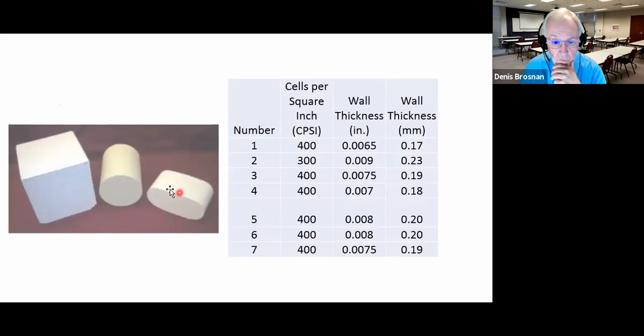The honeycomb products come in different shapes and sizes and all have open cells for the gases to flow through, whatever gas is being cleaned up. Automotive exhaust or other industrial gases can be cleaned up with these types of products. And typically in the smaller products, we'll have 400 cells per inch, and the wall thickness can be down here about 0.17 millimeters. That's 170 microns up to about 0.23, 230 microns. 170 microns means that the wall is approximately 170 particle diameters thick. So that's not a very great thickness. So some of the thinner ceramics that I've been involved with.